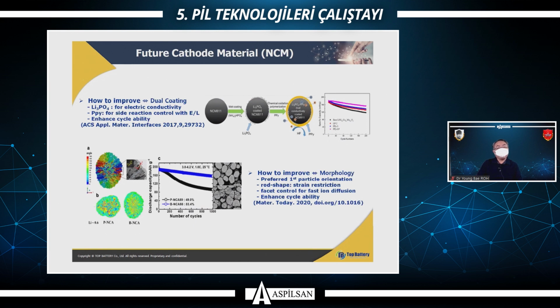The final option is morphology control. We have to prepare the primary particle orientation in a rod shape, to release the crystal structure strain, which is accumulated by the crystalline expansion and contraction during cycling. At the same time, the control of the C-axis is effective for fast ion diffusion. It leads to enhanced cyclability. All these kinds of approaches will be effective for cyclability enhancement and high capacity batteries.